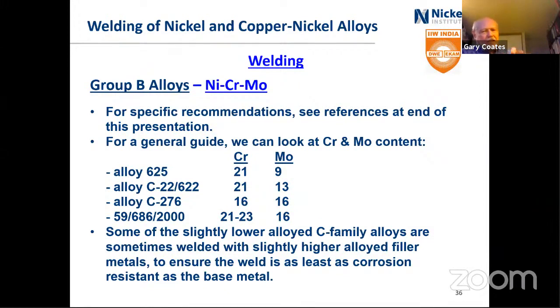The older C276 had a lower chromium content, but really high molybdenum content, so it's used in strongly reducing conditions. And then the other C-type alloys like 59, the VDM version, 686 special metals, and 2000, a newer Haynes one, has both the high chromium and the high molybdenum. So you can just think that if you're welding 625, you can easily use from a corrosion point of view a C22 or a 622 filler metal there strictly for corrosion resistance. Now, it's a bit complicated because 625 is also used for high temperature applications, and there, of course, it's a completely different situation.